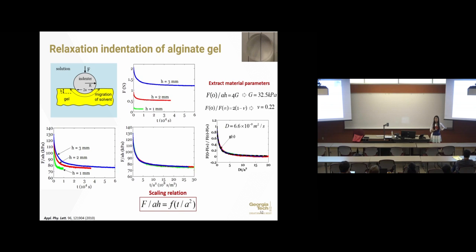So this is different from viscoelastic behavior. For viscoelastic behavior, the time character should not depend on length. So this actually proves that the time-dependent behavior of gel is mostly dominated by transport behavior rather than viscoelastic reconfiguration of the polymer chains, very different from polymers. So then, indeed, we normalize the t by a squared, length squared. This is diffusion, right? Diffusion length squared. They collapse into one single curve.